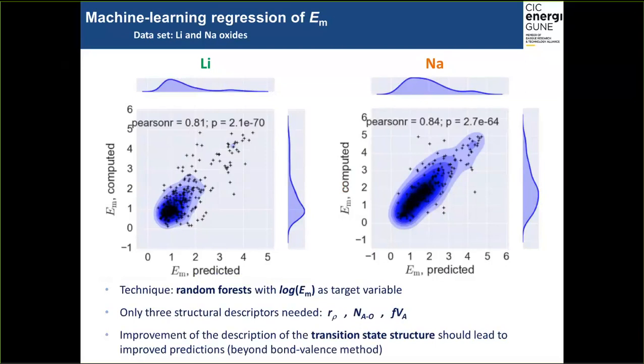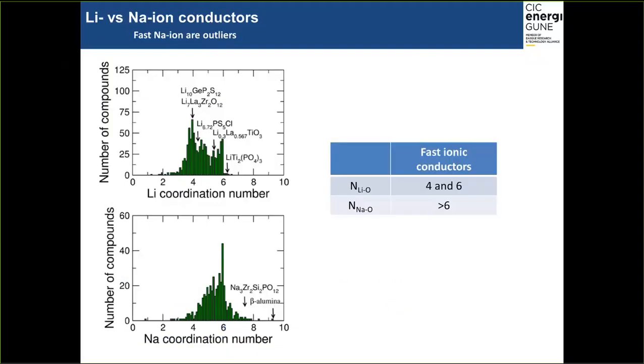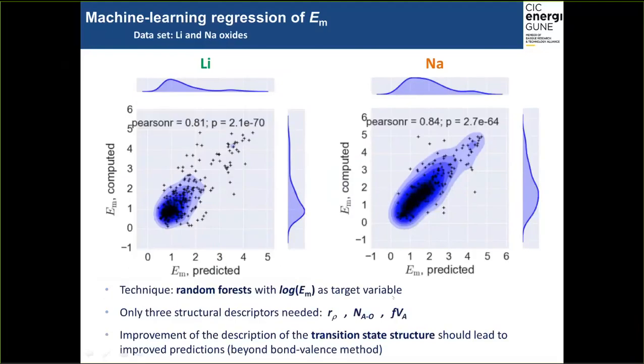However, current predictors describe well the initial and the final states of the hopping process for diffusion, but not the transition state, of course. The percolation radius provides some information about the transition state, since it provides the size of the bottleneck, which is usually located at the transition state. However, information about the coordination of the ion at the bottleneck is missing.